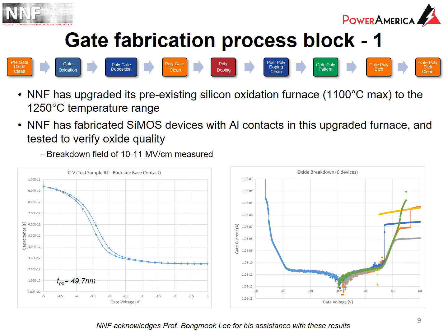We wanted an oxide thickness of 50 nanometers. We were able to hit it at 49.7 nanometers, which is great. And we were also able to get the oxide breakdown field at around 10.5 megavolts per centimeter, which is exactly what you would predict as oxide breakdown. So we were able to demonstrate that, at least for silicon, we were able to get the oxide quality that we needed from the new furnace.